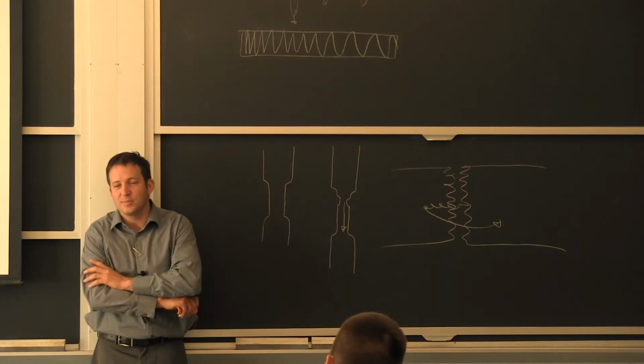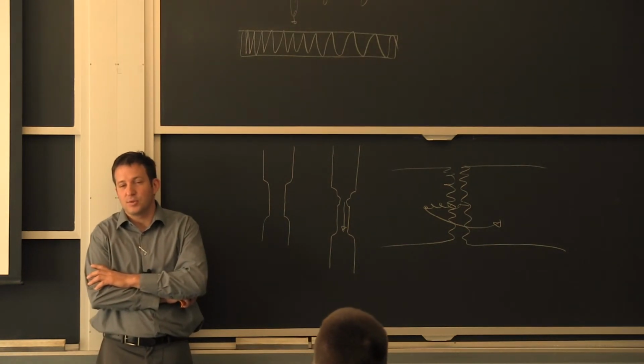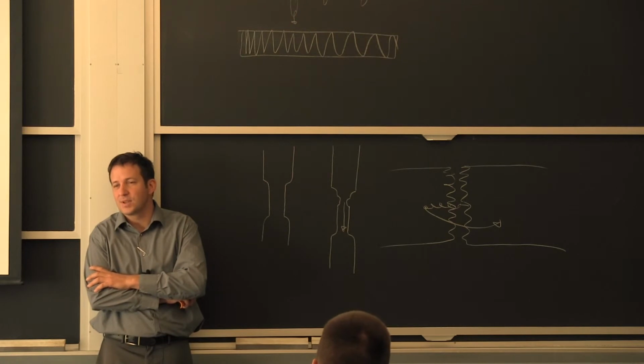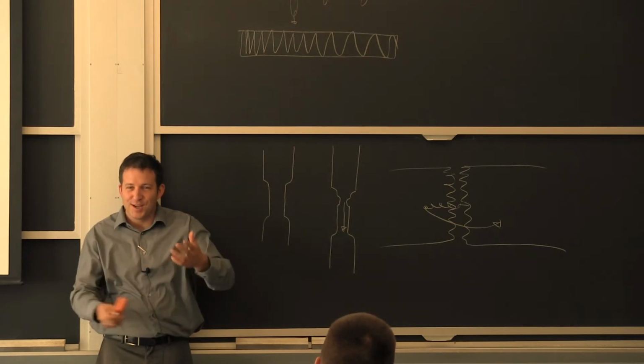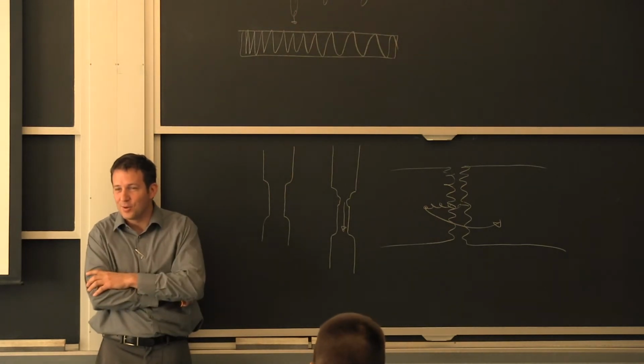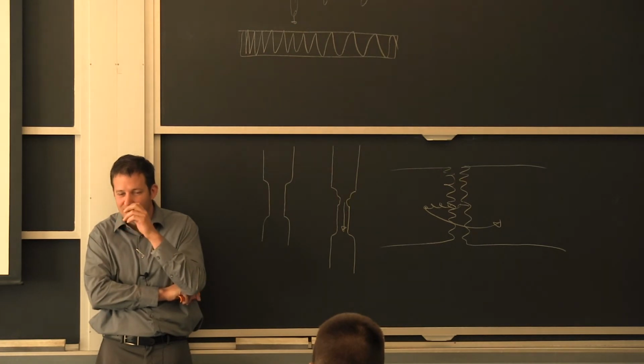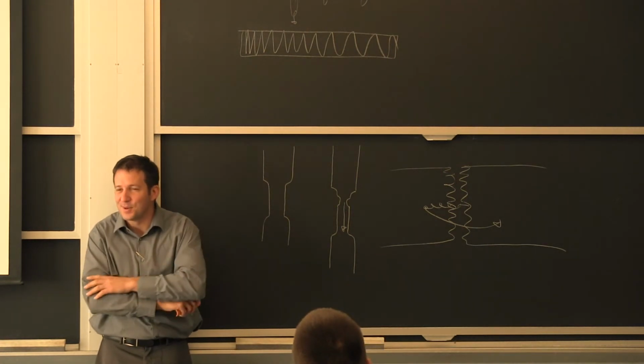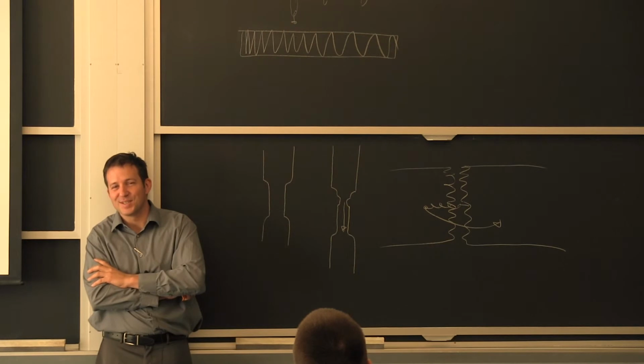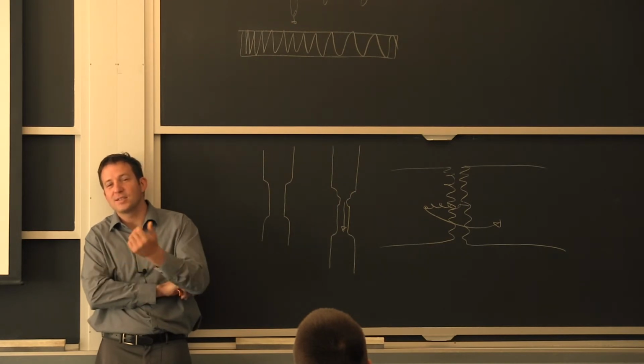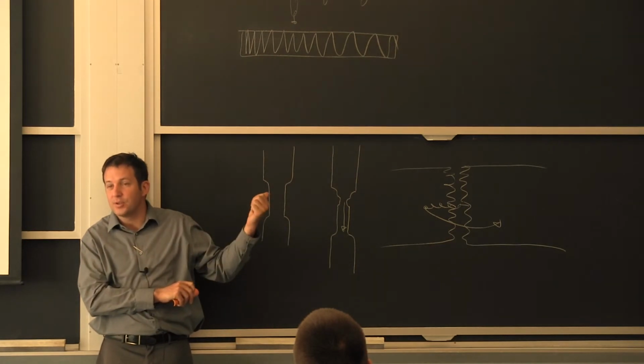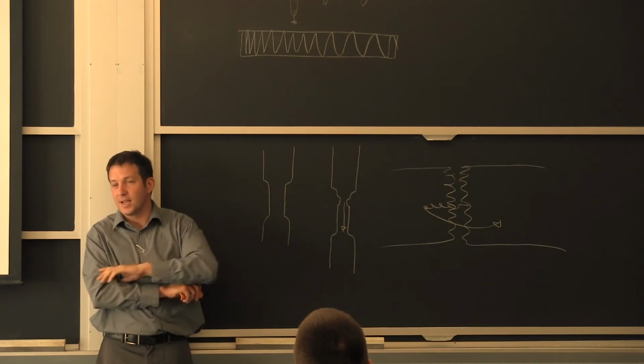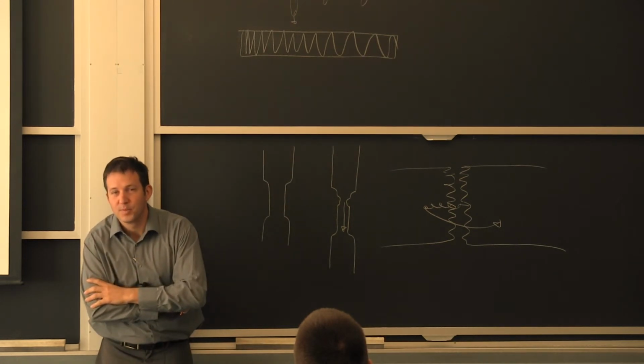So a lot of times the ASTM standards will give you a viscosity, a melt viscosity index that just kind of tells you a little bit how long the chains are, but they won't give you a number most of the time. So you almost have to test the properties, the creep properties, to know that you got exactly what you were looking for. Yes?